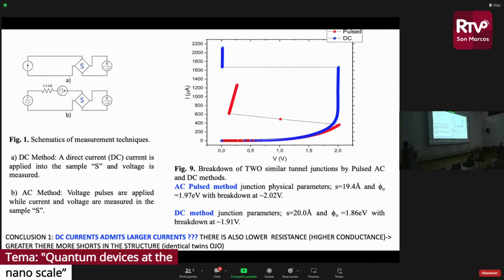You can see that the red is the pulse current, and the blue line is the direct DC current. This was surprising because we expected that with pulses of current you have time to cool down your tunnel junction, and so you would get lower voltages and lower currents. What you see over there is the breakdown, the destruction of the tunnel junction when you increase voltages. By the way, normally people don't get to those voltages because they don't want to break their devices, and it's very difficult to have the quality to do that. But we were able to go all the way to the highest voltages possible, and it turned out that the DC direct current method had larger currents, extremely large, as you can see, that got through there.